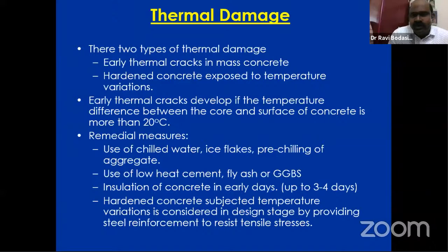Insulation of concrete is nothing but we have to cover with thermocol sheets or PP sheet covering, so that the temperature difference between the atmosphere and the core temperature inside the raft should not be more than 20 degrees, and we have to maintain that. Then only the structure will have more dense concrete, and it gives a more and more durable lifetime to the structure.